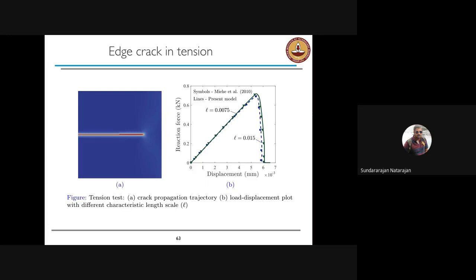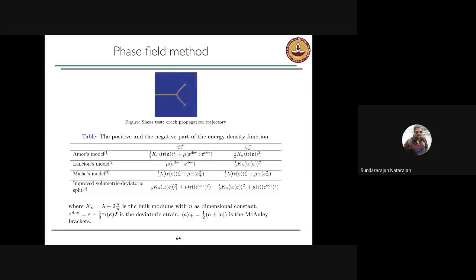So the red indicates the crack, and what I'm showing here is the phase field variable. Blue represents zero, which implies the rest of the domain is not damaged at all. We implemented that in our in-house code, and we compared the load displacement curve with what's published in the literature. We are able to get a good match. So in the case of shear, if we directly use the phase field formulation that was put forth in the earlier work, you see that the crack branches. And this is unphysical if you are talking about quasi-static crack growth.